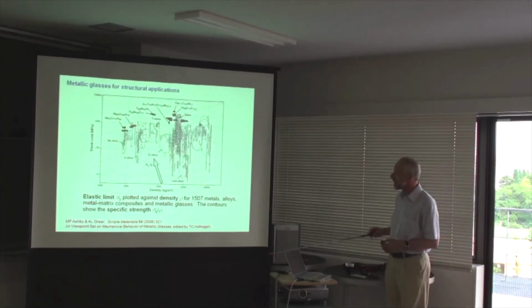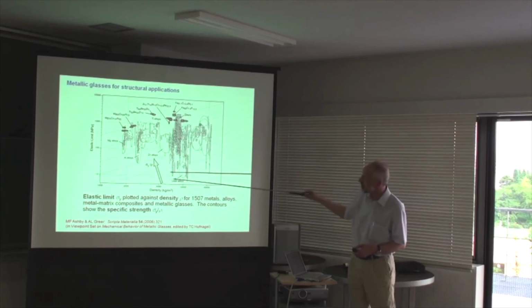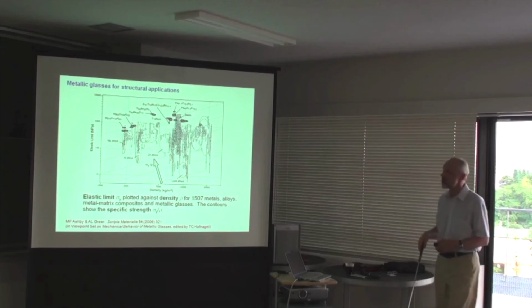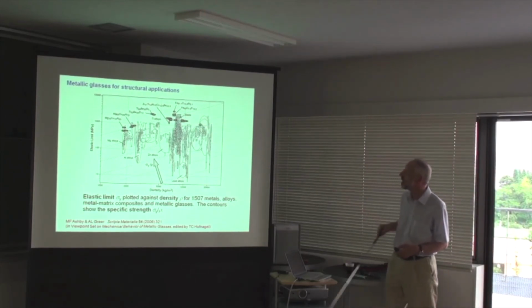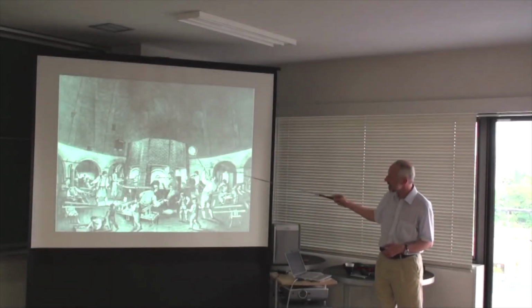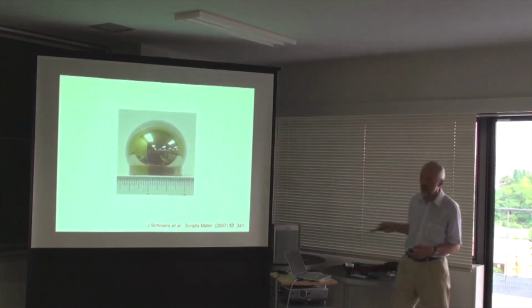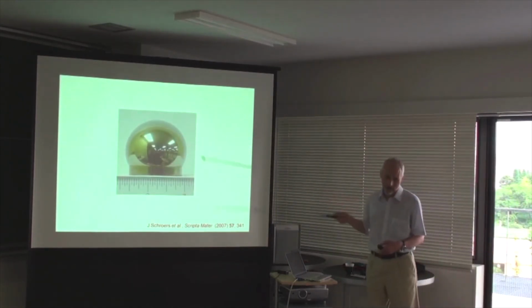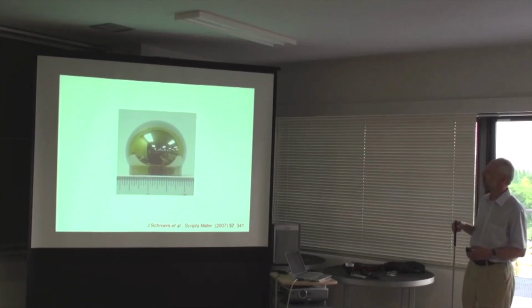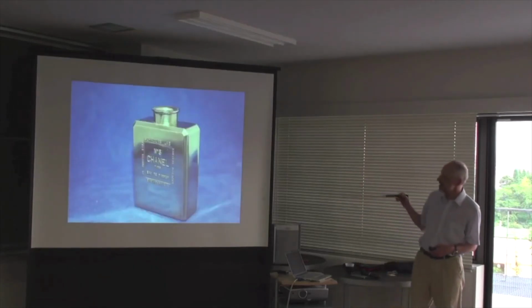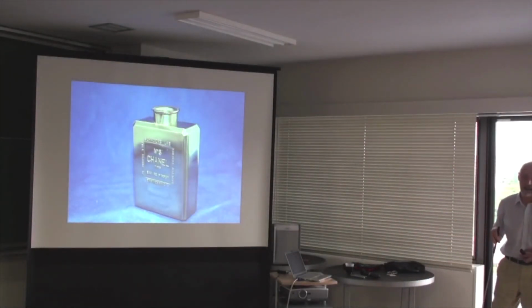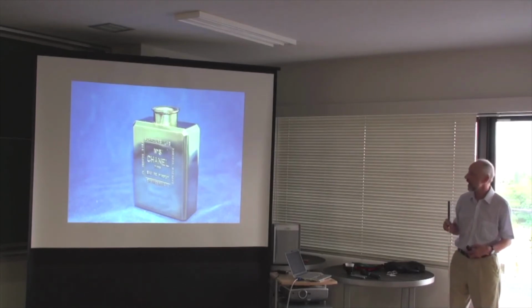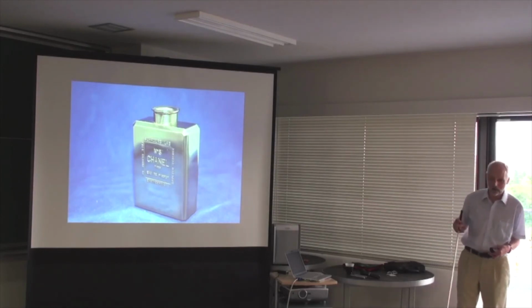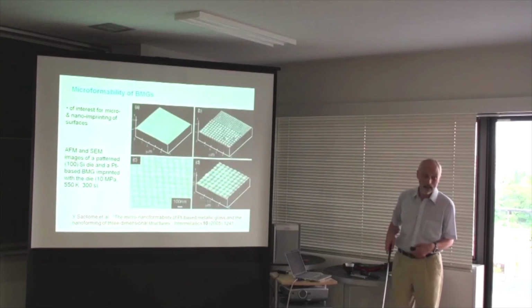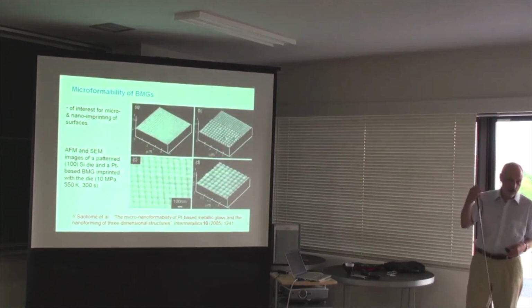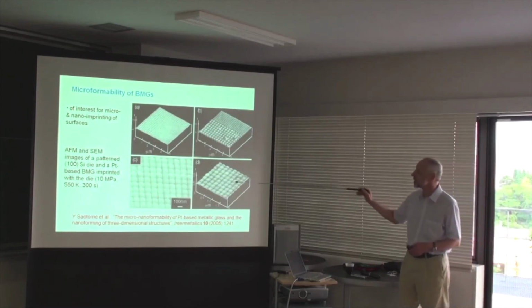Metallic glass is quite useful for lots of things because they have very high strengths. This is a chart of the elastic limit, the strength for metallic engineering materials in general, and the metallic glasses come at the top. This is of course for oxide glasses, historical picture, but you can do the same thing with metallic glasses. And maybe this is not a very interesting shape, maybe the next one won't be very interesting either, but the concept of Jan Schroers at Yale is that you're able to make shapes with this sort of glass blowing technique that would not be accessible to metals otherwise. Whether you will actually be able to buy these in the duty-free in the airport, I'm not sure. We'll see. And work here from Japan, because the glass has no internal grain boundaries, you can pattern the surface with a very fine pattern.